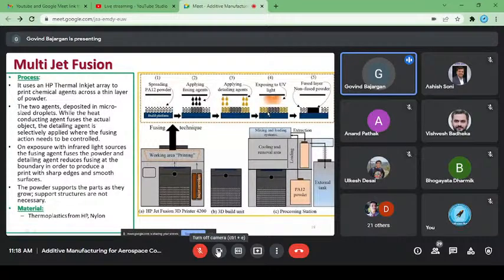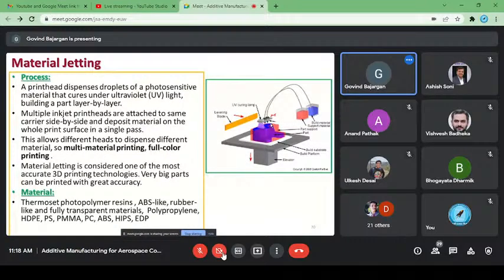And when we come to material jetting, here the print head dispenses droplets of photosensitive material that cures under ultraviolet rays, building the part layer by layer. Multiple inkjet print heads are attached to the same carrier side by side and deposit the material. Here we can see the print heads deposit the material, and there is a UV lamp. As it moves, wherever this photosensitive polymer is sprayed, the UV lamp will cure it, and this way, layer by layer, the 3D component is built.